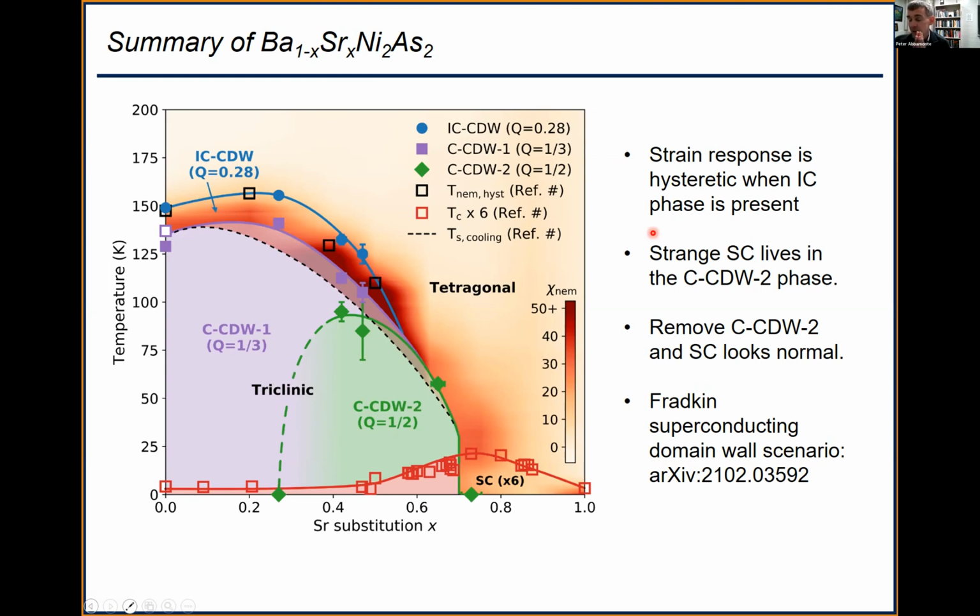I mean, it's a fair point. If it's truly incommensurate, the unit cell is infinite, and then crystallography doesn't even make any sense. And if you really want to get into crystallography, there's a superspace group formalism that was developed in the 90s by Sander van Smaalen and others, where they generalized the concept of a space group to things with incommensurate phases, and they actually refined the structure of tantalum disulfide doing that. It's a brilliant set of papers from the late 90s. If you want to do it right, you would have to index this using that framework, which is sort of beyond space groups.